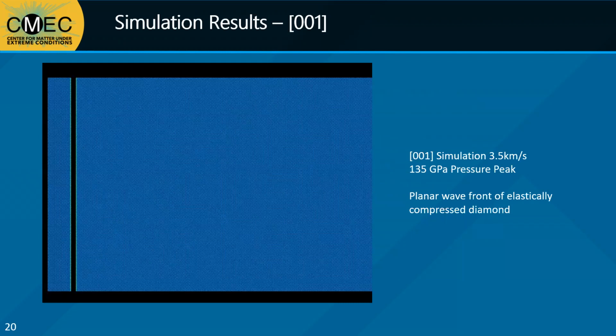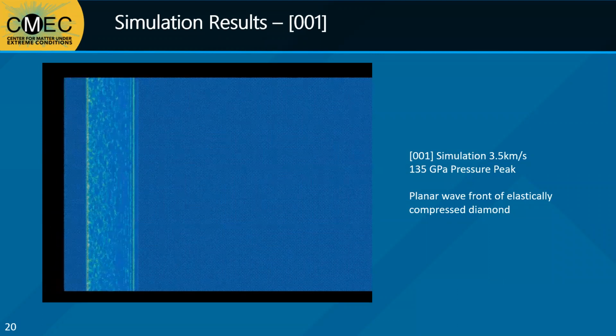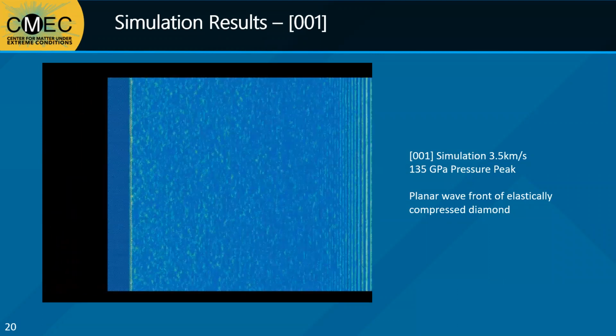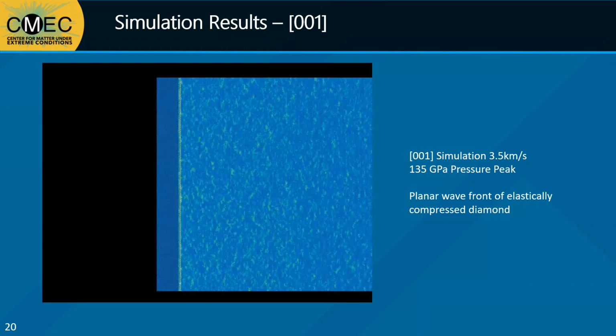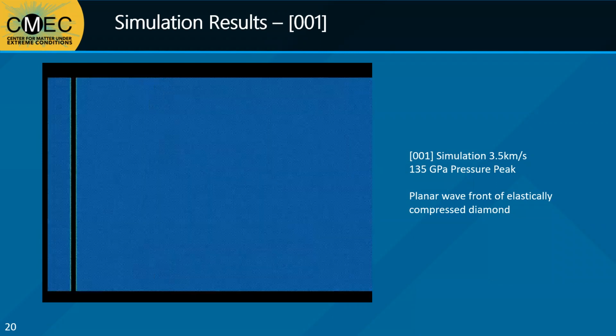For the 001 direction, our simulation results agree with what we see experimentally. As before, blue means diamond cubic, while light blue and green mean first or second nearest neighbor diamond cubic. Even at 3.5 kilometers per second, resulting in a peak pressure of 135 gigapascals, we see that no dislocations or defects are forming, just pure elastic compression.